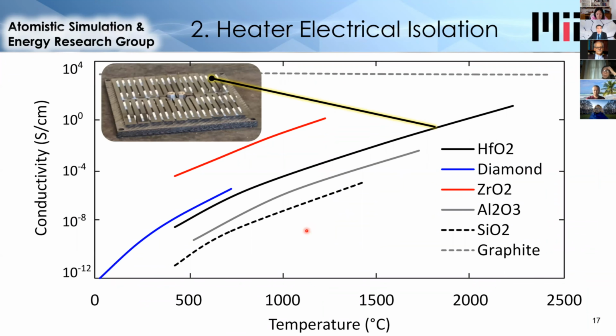So the next thing to consider with the heater is how to electrically isolate it. So first, using a tungsten heater shown here, it's this thin heating element that needs to rest on a surface beneath it that doesn't conduct electricity. And so these curves shown here are different materials' electrical conductivity versus temperature. And I wanted to select a material that was resistive, much more resistive than the heating element itself, at up to 2,500 degrees Celsius. But as you can see, most of these curves stop well before that temperature because the materials decompose. And so hafnium oxide was the only candidate material that has been determined to survive at least nearly to this temperature, around 2,300 degrees Celsius.